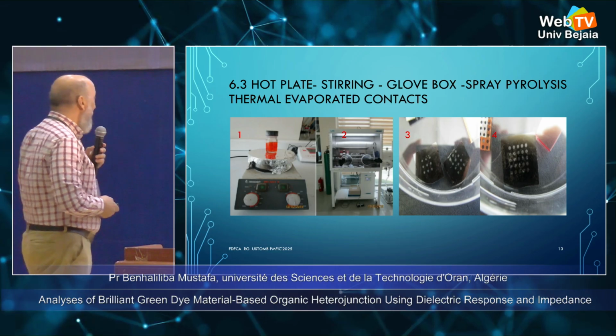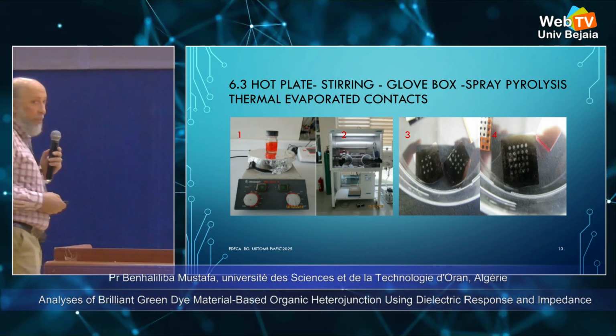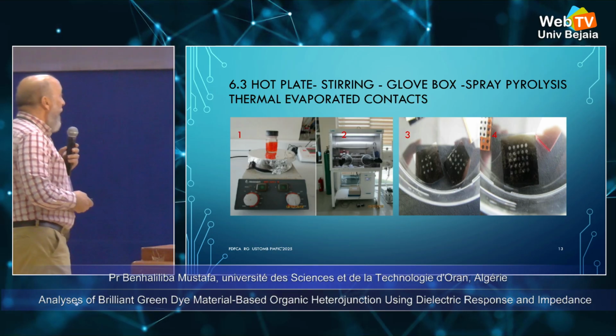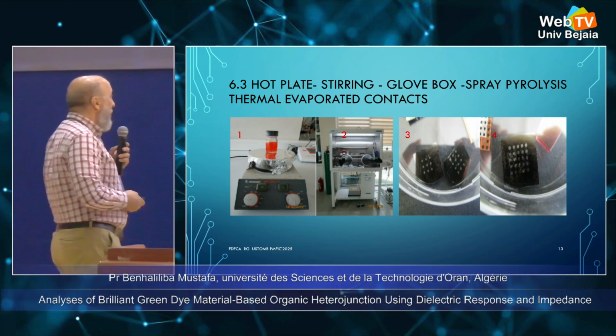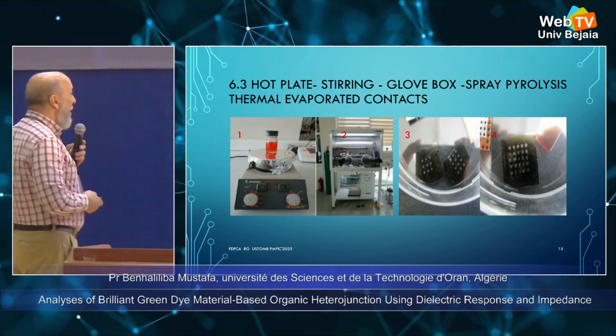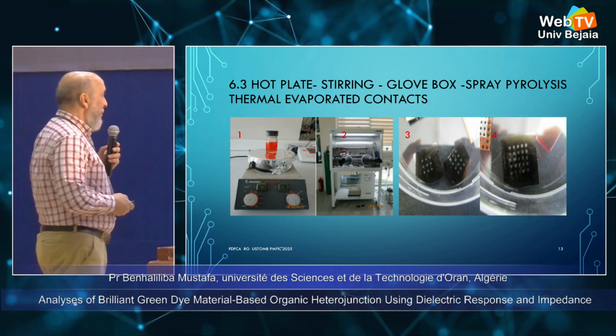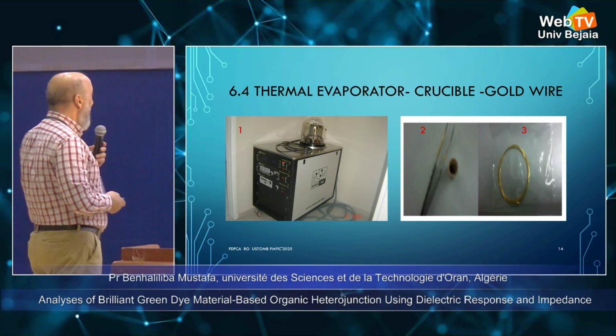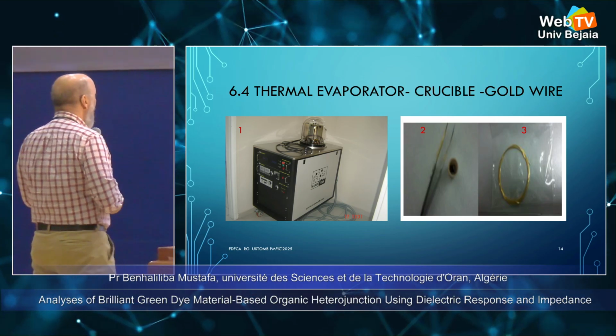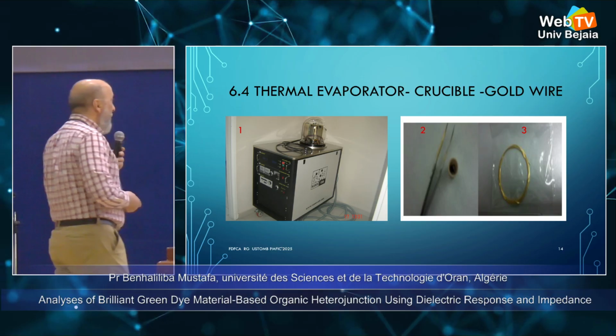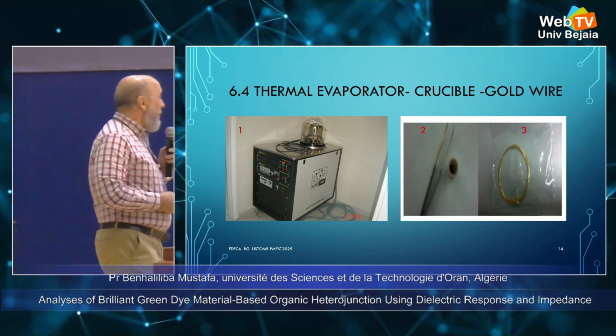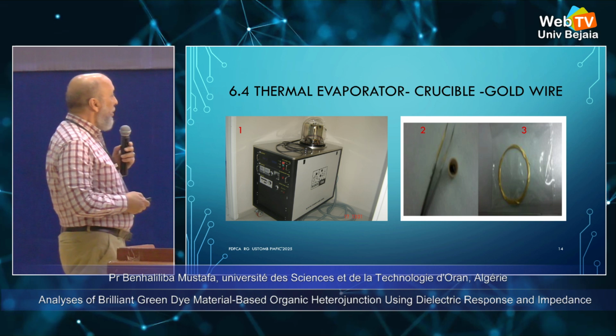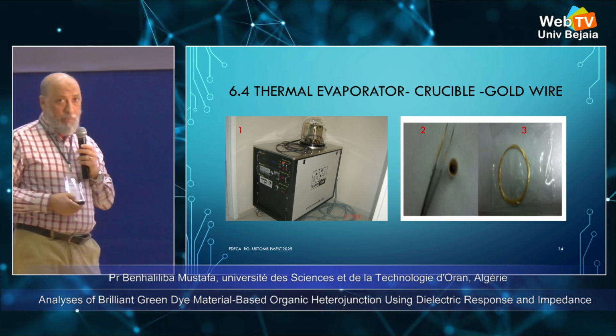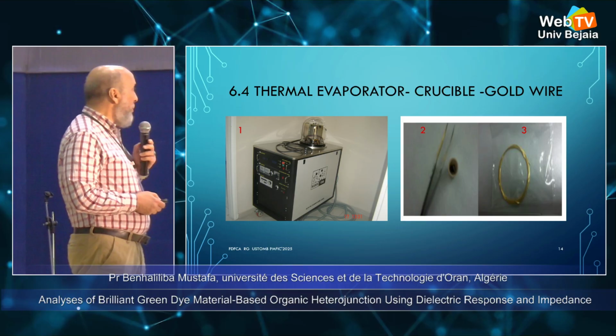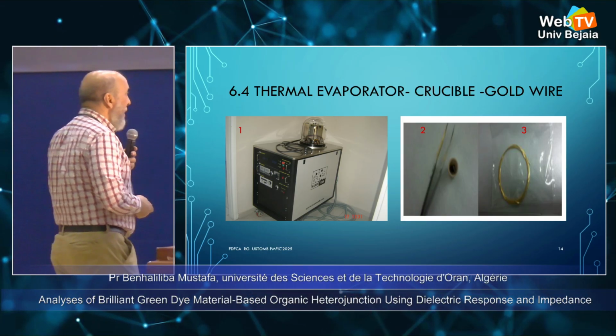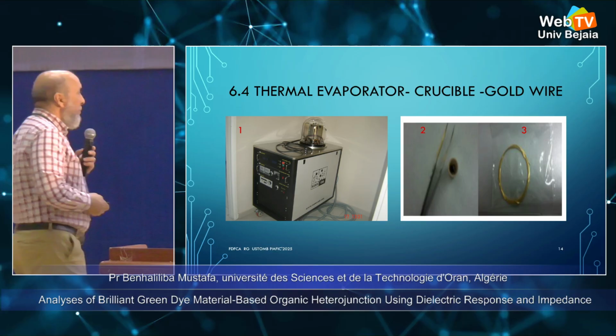Here in figure 1, we have a hot plate for heating and stirring the solution. In 2, we have the glove box to prepare. In 3 and 4, we have the fabricated diodes. In this figure, we have in 1 the setup of the thermal evaporator, and at right, we have the crucible. We sometimes use the crucible to anneal the powder in the furnace, and we have the gold wire for the contacts.